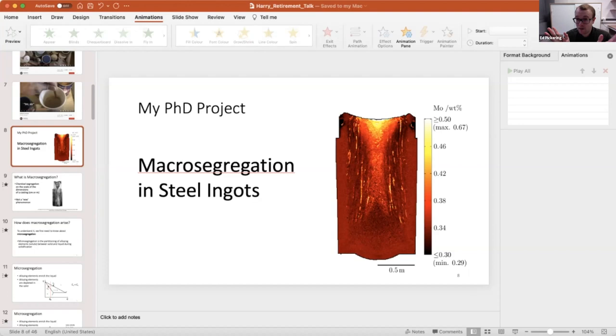And what we have to do is essentially just design it out or engineer it out and deal with it. So what they do is they chop, hopefully you can still see my screen here, they would chop off the top of this ingot. And maybe some people with this French case didn't chop off as much of the ingot as they should have done, but that's just speculation because I don't actually know what happened. But you usually chop off the top, say, 20% of the ingot, and that removes a huge amount of segregation immediately. And then also you can punch out the middle of the ingot, and you can essentially machine away bits and pieces.